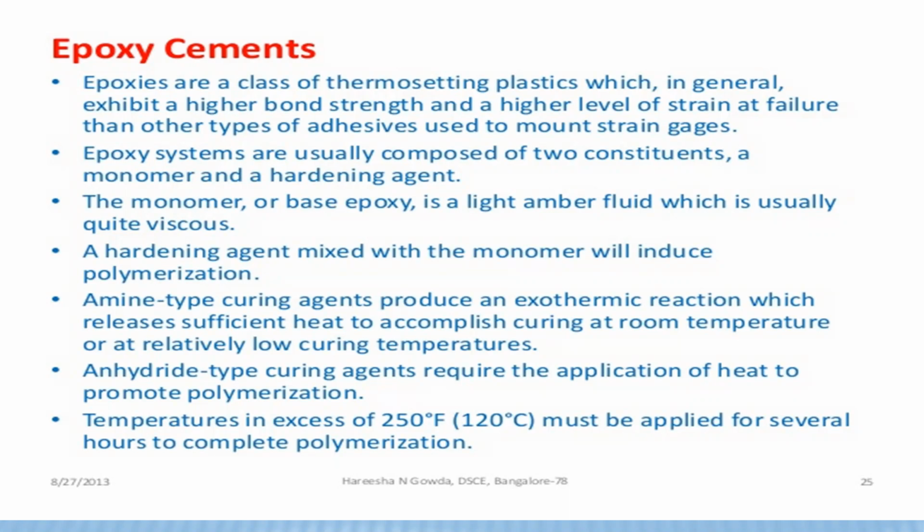Amine type curing agents produce an exothermic reaction which releases sufficient heat to accomplish curing at room temperature or a relatively low curing temperature. Anhydride type curing agents require the application of heat to promote polymerization. Temperatures in excess of 250 degrees Fahrenheit, that is 120 degrees centigrade, must be applied for several hours to complete polymerization.